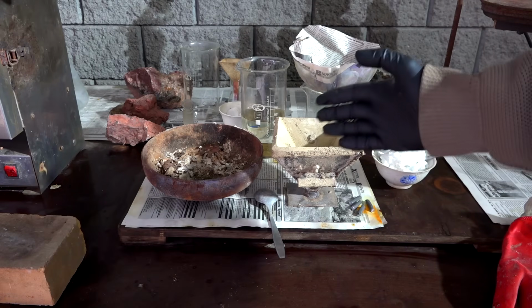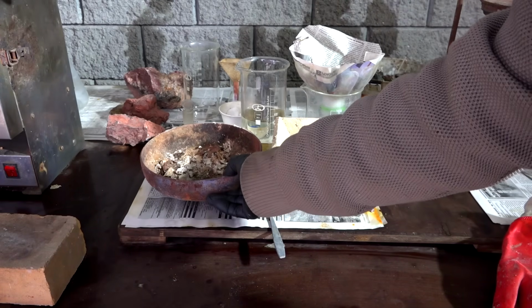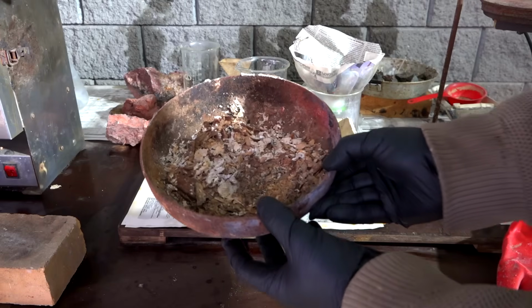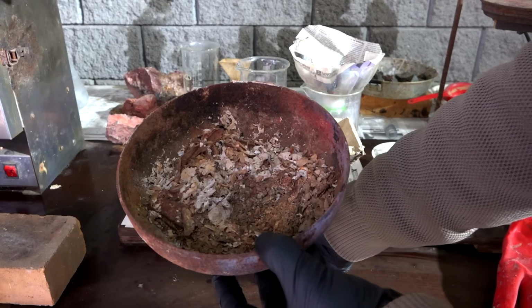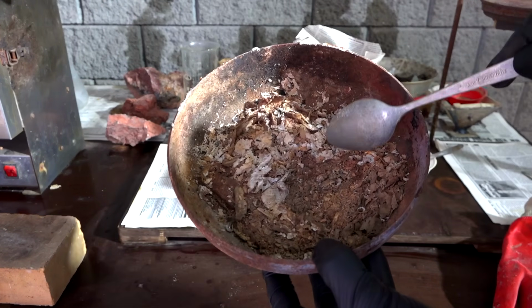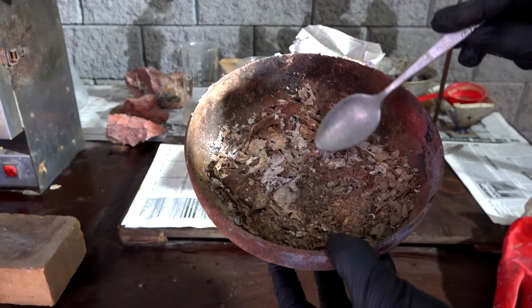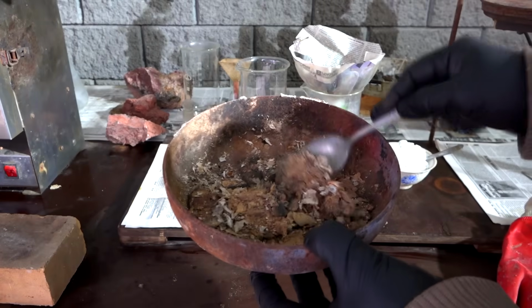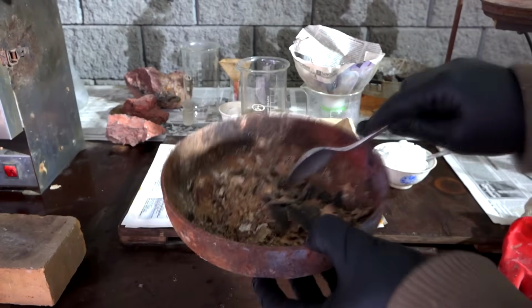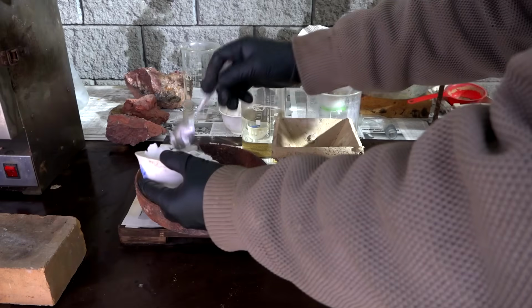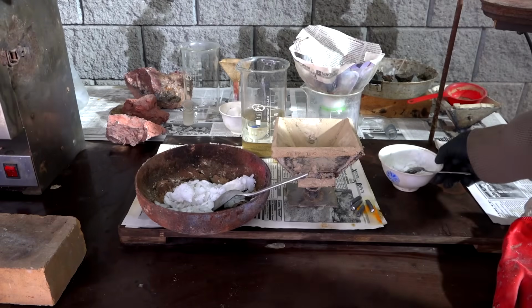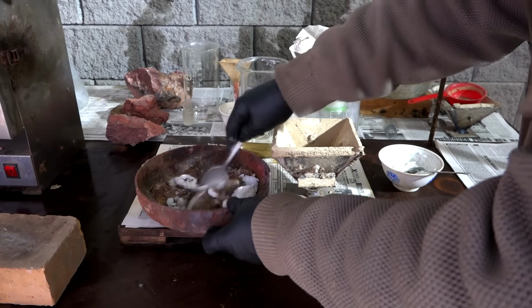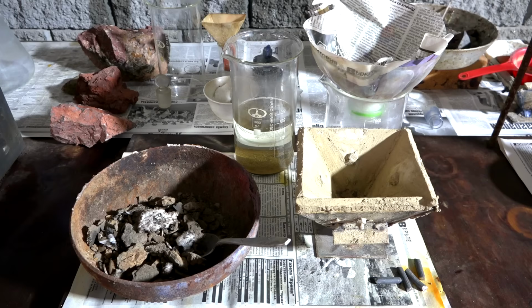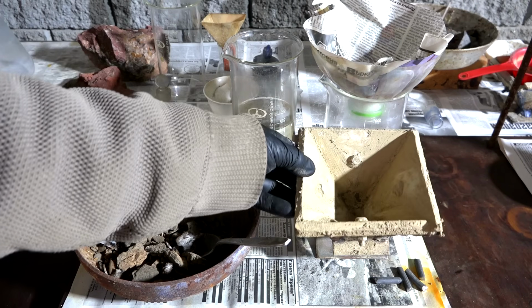After firing, I carefully examined the contents, and here's what I know. The yellow particles are still visible and have a characteristic metallic color, similar to gold, with slight variations. Numerous silvery particles are also visible, making their identification difficult. Because the material was heated to red heat, the particles exhibit a rainbow of colors. This effect may be due to oxide films that form when metals are heated.